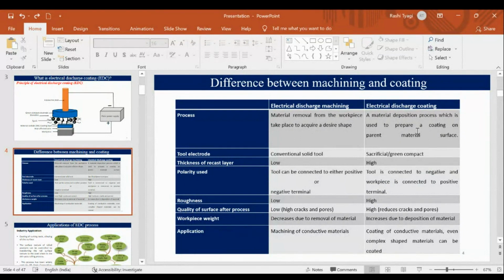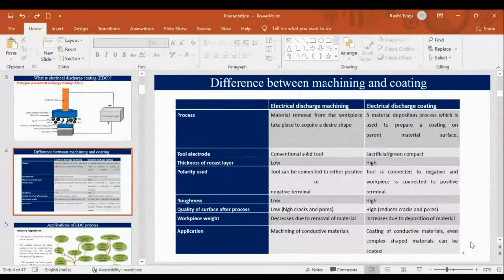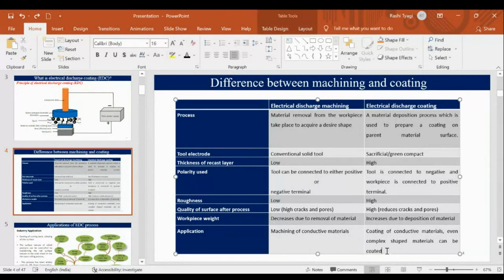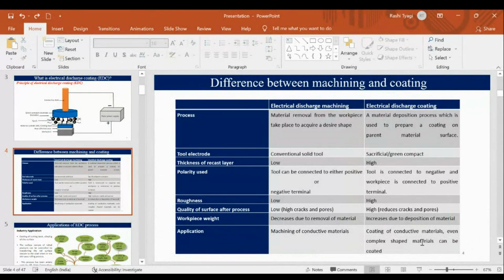Workpiece weight increases after EDC as the thickness increases. Application: machining of conductive materials and coating of complex shape workpieces can be done by the EDC process. Why? Because we can make the green compact tool in any shape. You can use the powder, take any form of die, and compress the powder in the shape that you want to obtain. So for any complex structure that you want to be coated, you can use a replica of that structure, in the hot mounting press or by making dies of that structure. So this is one of the main excellent applications of the EDC process.